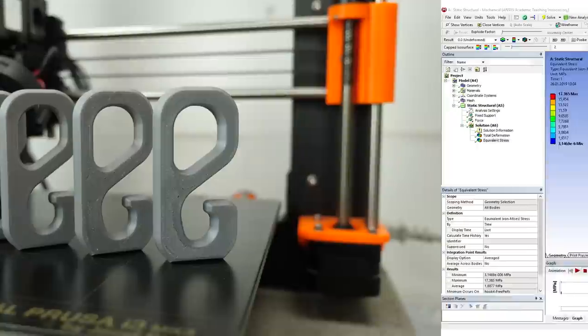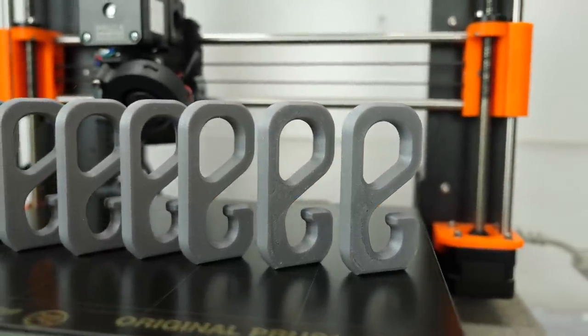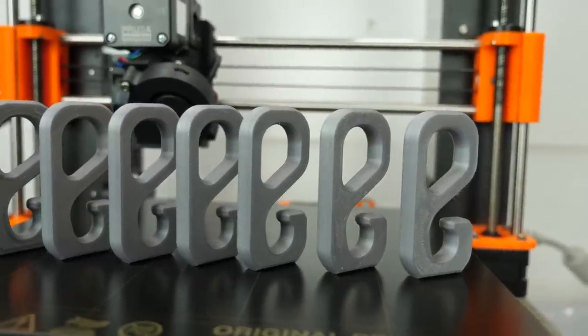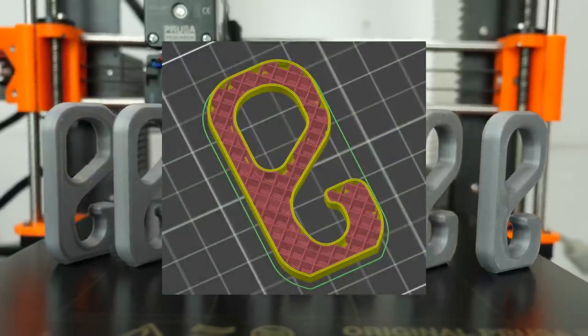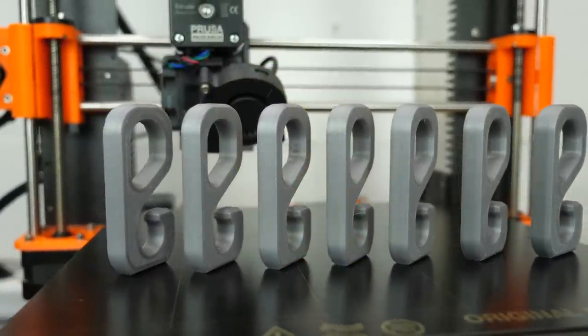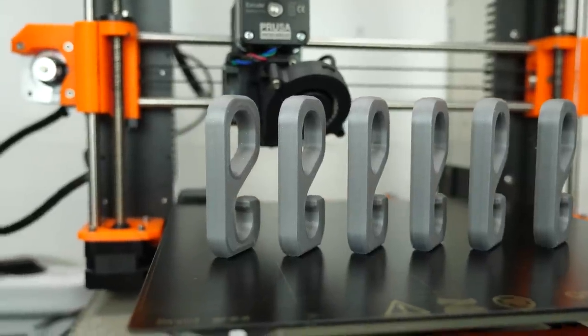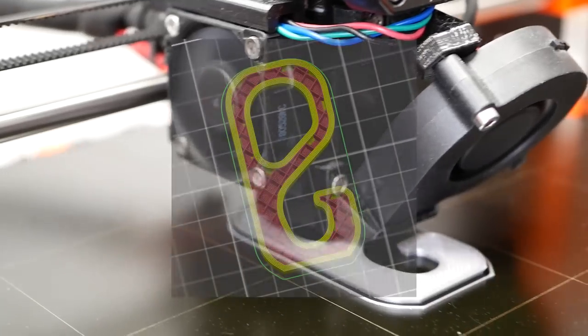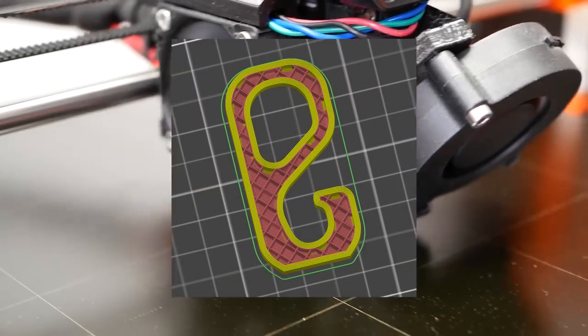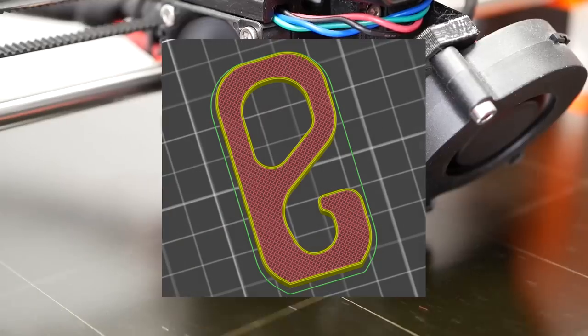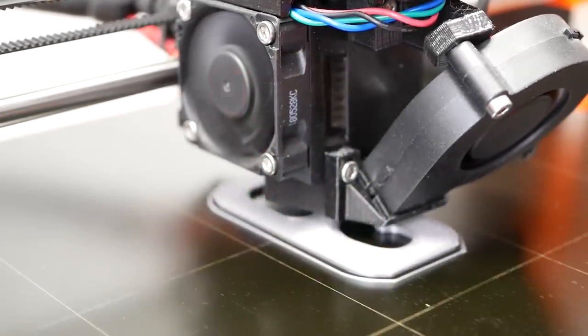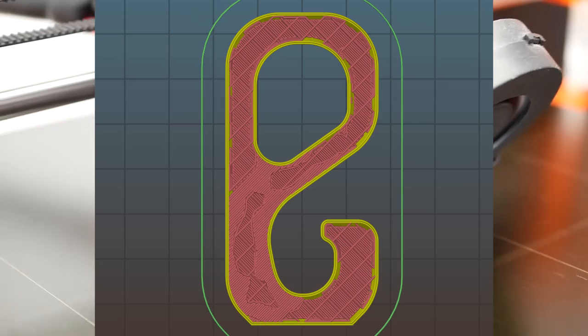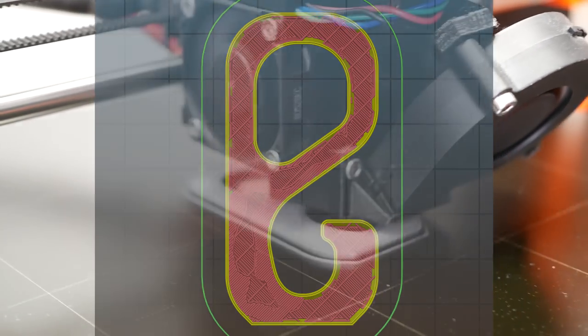To see if the method really works, I applied it to my test hook that I usually use for filament tests and other studies. The starting point is the hook with two perimeters and 10% infill. Usually you'd increase strength by increasing the number of perimeters or the infill ratio. One hook has five instead of two perimeters. The other still has two perimeters but 42% infill, which results in the same weight as the one with five perimeters. The hooks with smart infill also all have the same weight as the last ones, so we can compare them properly.